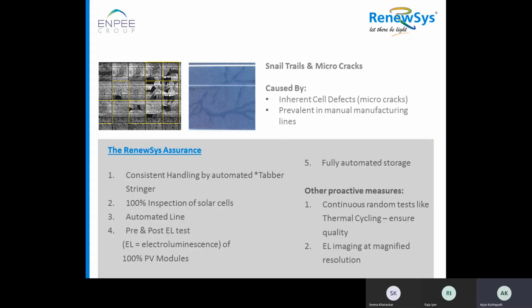100% inspection of solar cells. As you know, we have cell manufacturing in Hyderabad. We do 100% EL before packing the cells, and those cells are again checked in the tabber stringer with a visual inspection system. After making them into strings and bussing, they are checked again at pre-EL, then go to lamination, and the EL is checked again post lamination. So there are multiple stages where we check our EL system and ensure 100% good cells are processed, and our lines are automated. We don't have any manual handling in the line. It's completely automated, and the strings are even handled with robots.